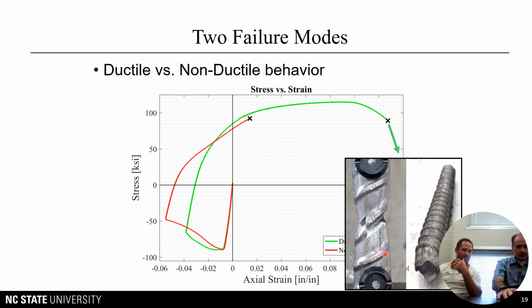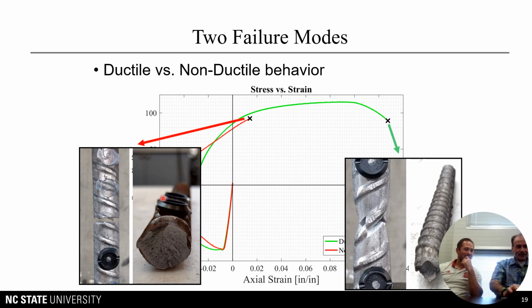Yeah, so that would be the ductile. You see necking. And this is more brittle, right? So there's not a lot of necking. I'm not a metallurgist, but basically it looks like there's an explosion coming from the top half here. This is the inside point of the buckle, where the compressive force is the highest, and that's what we were really looking for: where is this critical bending strain that resulted in the ductile or the brittle fracture?